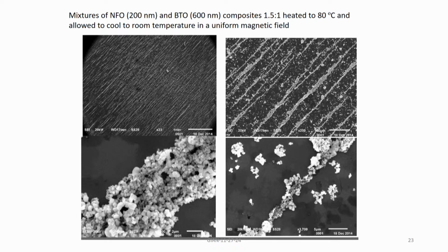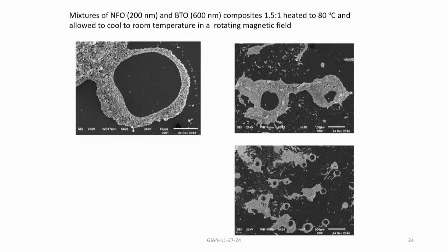And these are at different concentrations. Initially they were heated up to 80 degrees, so they dehybridize. Then apply a magnetic field and cool them down, and they hybridize and line up along the field direction. Especially this one looks nice. We also assembled this in a rotating magnetic field. The magnetic stirrer was just rotating. You spread these particles and you see nice rings of these coarser particles under a rotating magnetic field.